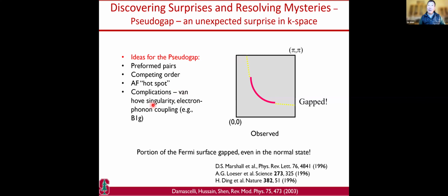There's a van Hove singularity, which distorts things. And we also know that there's antiferromagnetic scattering, that's the antiferromagnetic hotspot. Then it is also known that electron-phonon coupling can be preferentially strong at the antinode. So there was a lot of debate on this issue.